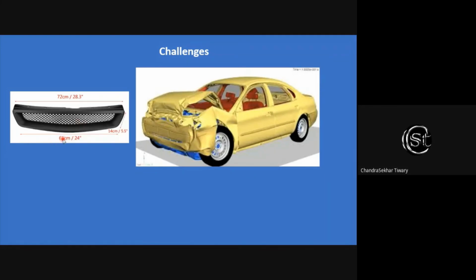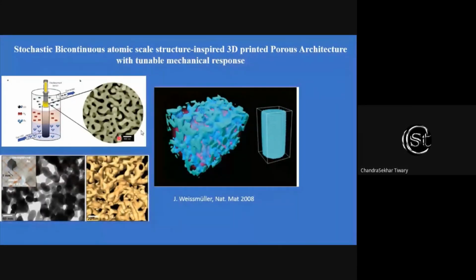We started looking at whether we can build a structure which can have controlled deformation. And one of the works, done by Weissmüller in 2008, is that they take gold and copper nanomaterial, mix them and make a structure out of it, and then they dissolve one of them, mostly copper. They etch out the copper, and what is left is a very complex structure. Now these are at atomic scale. We are talking about the 100 nanometer range. Each of these blocks is a couple of nanometers, and the TEM shows around 20 to 50 nanometers. The idea is, now we have a solid structure. Can we take this atomic scale structure and see if we get the advantage of this topology at a higher scale?